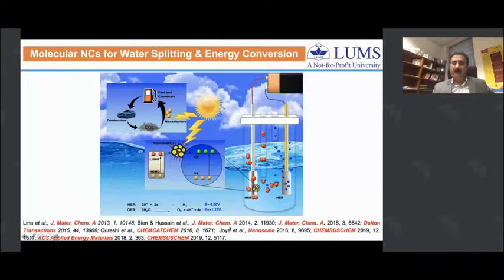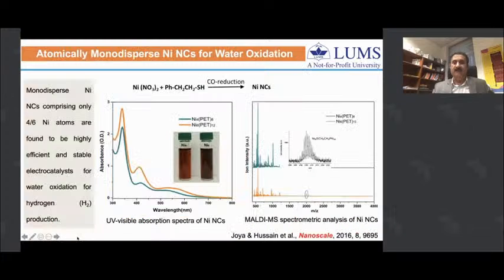For this purpose, we worked on a variety of new transition metal and metal oxide nanoclusters. For example, we started with nickel nanoclusters. In this case, you simply reduce nickel with carbon monoxide in the presence of phenylethanethiol, and by controlling the ratio of phenylethanethiol and nickel, we were able to produce atomically monodispersed nickel nanoclusters containing either 4 or 6 nickel atoms.